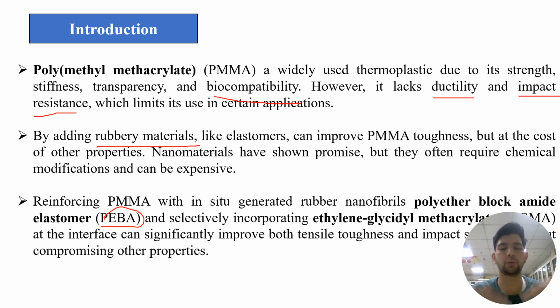The main thing is that PMMA is a very good polymer, a thermoplast, highly stiff, but the ductility is not good. So if we want to increase the ductility of PMMA or any polymer, we add some elastomer. If we add elastomer, the ductility will increase, but the strength and stiffness will decrease. By increasing one property, the other will decrease. So that is the issue. In this paper, the author tried to improve ductility and never lost the stiffness. That is the interesting thing.